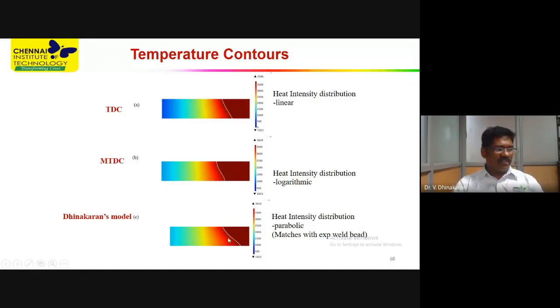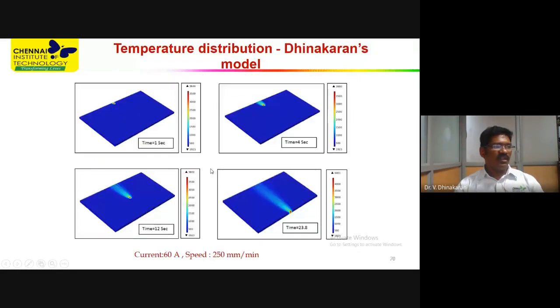On the temperature contours, the parabolic fashion has been arrived at by computational mechanics. We use Dinakaran's model rather than the others. And see the temperature distribution predicted by Dinakaran's model: the temperature is getting constant only when it reaches the quasi-static process, and the temperature is maintained constantly. But when the heat source reaches the end of the plate, the temperature is suddenly rising. The reason for the sudden increase of temperature is that while the heat source is here, there is area normal to the surface for heat transfer, but here there is no further area for heat transfer enhancement. Hence, the temperature suddenly rises from the constant to a certain extent.